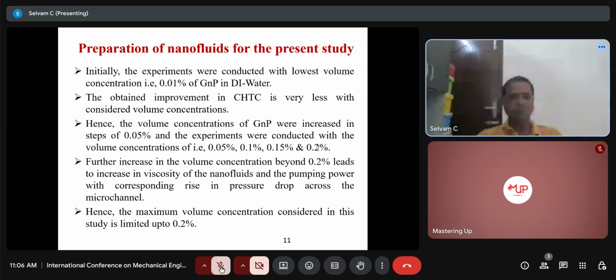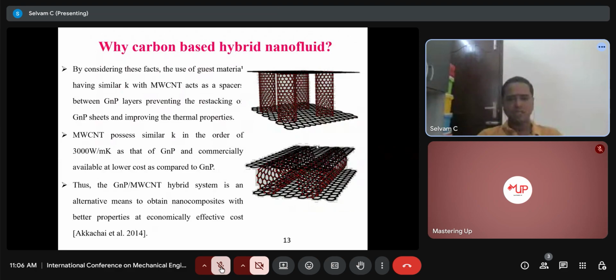That is why we have gone with the hybrid, as well as why we have selected carbon nanotube and GNP. A few researchers have gone with different nanoparticles like copper and carbon nanotube, silver and carbon nanotube, silver and graphene. Many of them have gone, but that won't be feasible based on our observation. It can be feasible based on their observation, but based on our observation, it won't be feasible. But technically speaking, we have selected graphene nanoplatelets. You can see this is graphene nanoplatelets, and the agglomeration of graphene nanoplatelets will be avoided. It will be arranged like this or like this. So agglomeration or stacking of graphene sheets won't occur in this particular hybrid nanofluid. So it will be feasible.